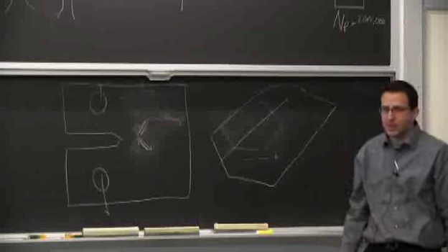it varies obviously if you're loading with your mean load. So if you're loading like this, it will happen. If you just say, oh, I'm going to load really like tension, then it's possible you don't have any closure of the crack. So that's why dealing with the first part of the curve is tricky, and to be conservative, we go more in what's called the Paris regime. The Paris regime is what gives us this equation here. This is the Paris equation for crack growth rate.